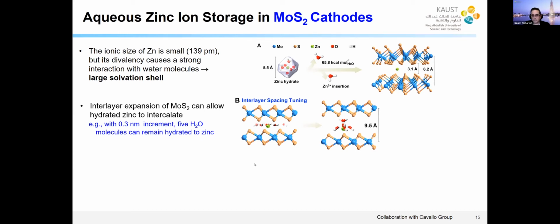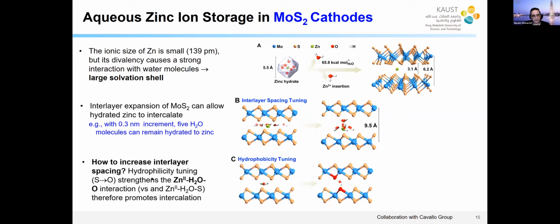So how do you increase the spacing? There are different strategies. One strategy actually is to try to tune the hydrophilicity. Basically, change some of the sulfur atoms with oxygen. The oxygen, when it goes inside the molysulfide, can actually help intercalation. This is zinc, hydrogen, water around the zinc. This is the 6-fold coordinated zinc. When it goes in, if it finds oxygen, it can bond to it easier than to sulfur. So we call this hydrophilicity tuning.